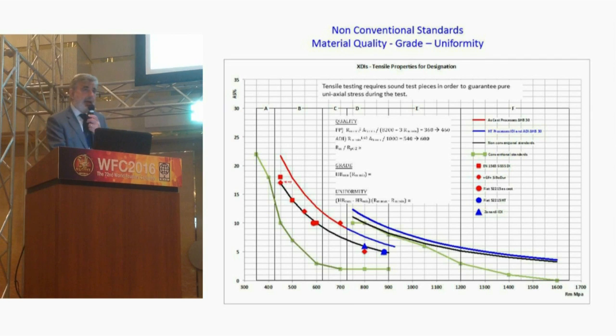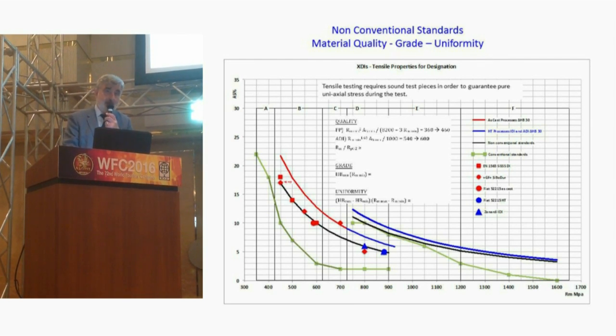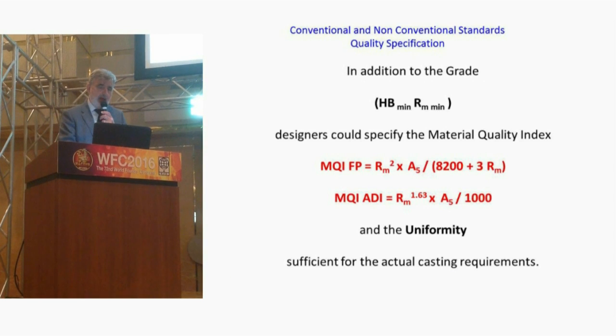And so the specification should be done by material quality index, grade, that is the minimum strength or the minimum hardness on the casting, and uniformity, that is the Brinell hardness range the designer allows on the casting. So this is what I said before, how I suggest to specify the new grades for the standards: specify minimum hardness or minimum strength, the quality index, and the uniformity.